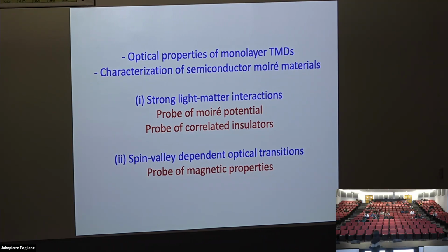How important is twist angle disorder? For homobilayers, twist angle disorder is a very significant challenge for the field. But for the heterobilayers I talked about, the period is mostly determined by the lattice mismatch. So this seems to be less of a problem, but of course it's still there, especially if you have strain or something, so that will give you disorder.